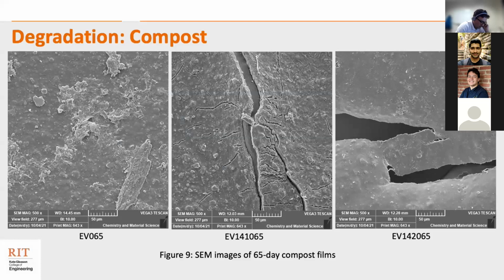Figure 9 shows a zoomed out view of samples that have spent 65 days in the compost. The extreme left image shows an untreated EcoVio sample, and it can be seen that there's a bit of soil and microbes on the surface, but other than that, there's no significant degradation that can be observed on the surface. Whereas the next two images show appreciable wear and tear, or degradation, on the surface. The 20-second plasma treated samples show large tears and cracks on the surface that measure about 200 to 300 microns.